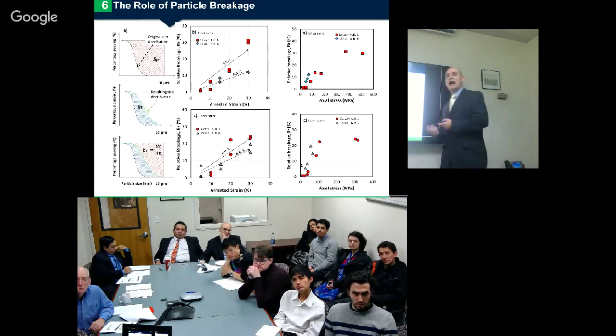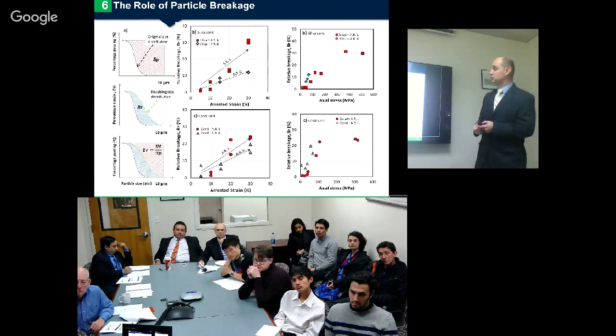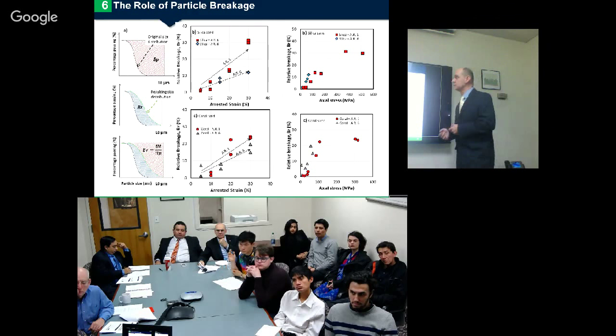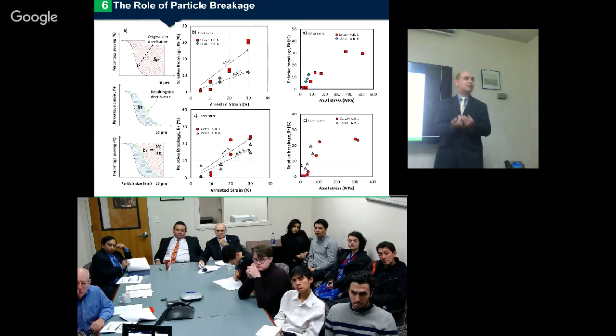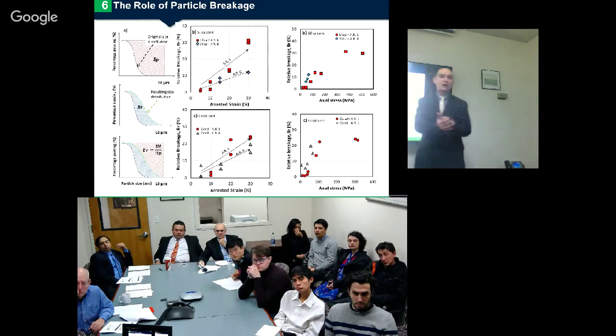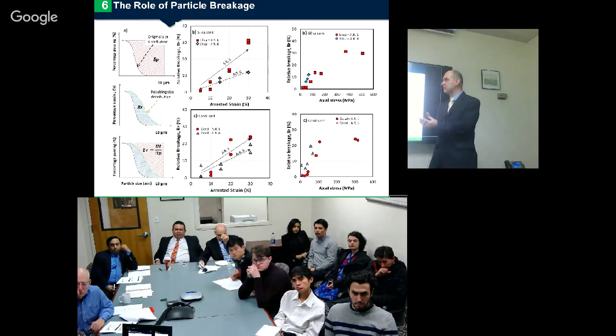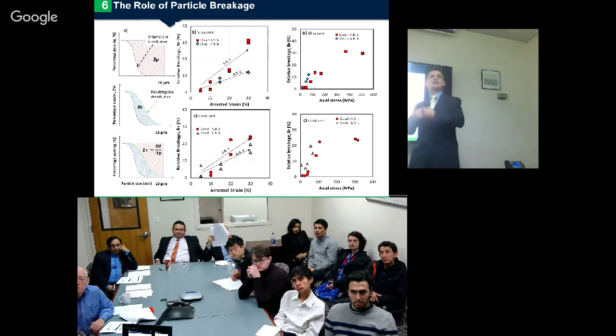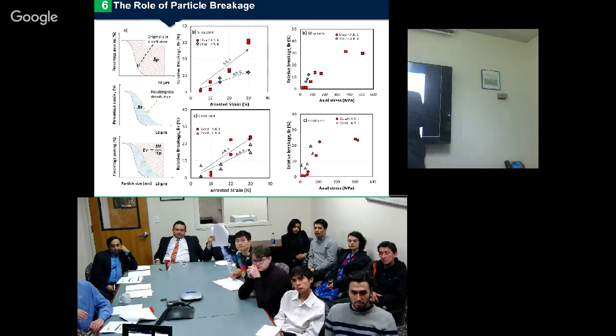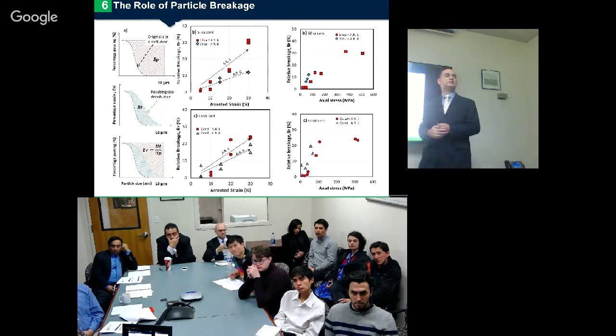And then by using Hardin's methodology to quantify particle damage, which is this one, Br, the relative breakage is the relationship between the total breakage of the sample at any given stage divided by the potential breakage that the material might have. So from this point up to this point that we set, we valued 10 microns. This is the potential breakage. This initial size distribution can shift all the way up to here if a significant amount of load and time is applied to the material.